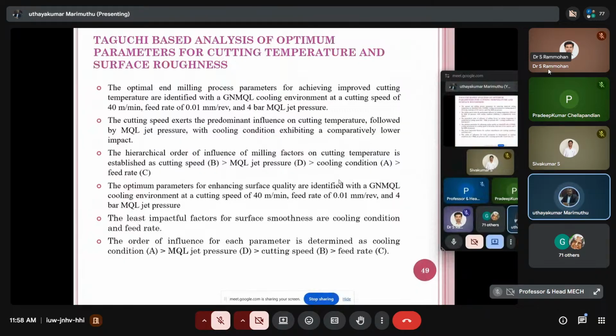The optimal end milling process parameters for achieving improved cutting temperature are identified with the GNMQL cooling environment at a speed of 40 meters per minute, feed rate 0.01 mm per revolution, and 4 bar MQL jet pressure. The cutting speed exerts the predominant influence on cutting temperature, followed by MQL jet pressure, with the cooling conditions exhibiting a comparatively lower impact. The hierarchical order of influence of milling factors on the cutting temperature, you can see that